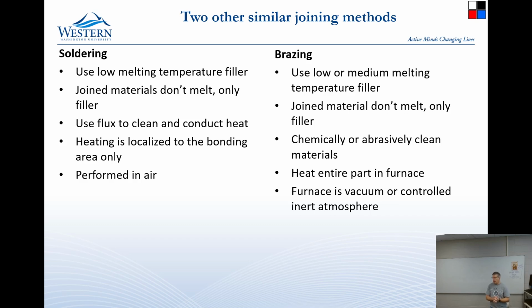Brazing is pretty cool. There are lots of times when brazing something together is a better way to do it. So what we do is you take something and you assemble it, and if you have a really tight joint between the two pieces, you put braze material around the outside, you heat it up, and the braze will actually wick up and through the entire joint. So it will seal together a lot more than you can with a weld. Because if you're doing a weld, you can only put it at the outside edge. You can't weld all the way through the length of a joint, especially if it's got kind of a crazy shape to it. So the place that a lot of this is used is if you've been over in AMSEC using things over there, or in vacuum furnaces, stuff like that.